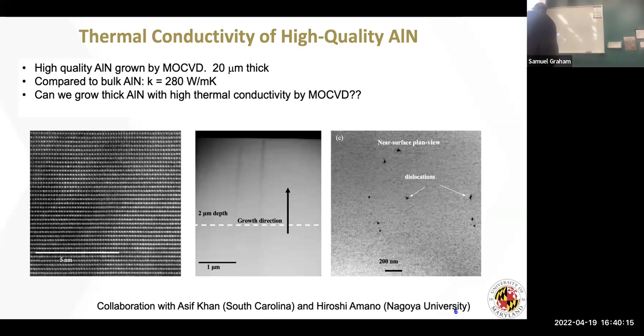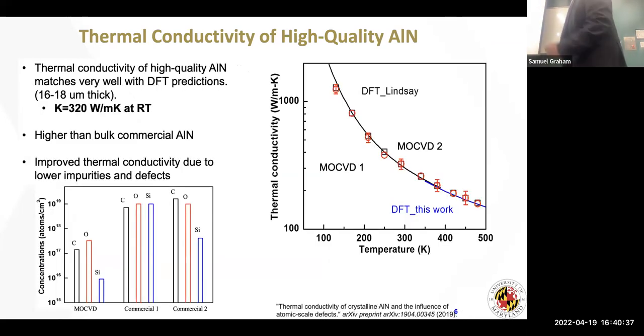He's figured out how to grow really thick layers of aluminum nitride by MOCVD. And so the nice thing about it is that by growing by MOCVD, so it's metal organic chemical vapor phase deposition, he can actually remove a lot of impurities. He can actually grow these layers tens of microns in thickness. And so when you do this, this is what we found.